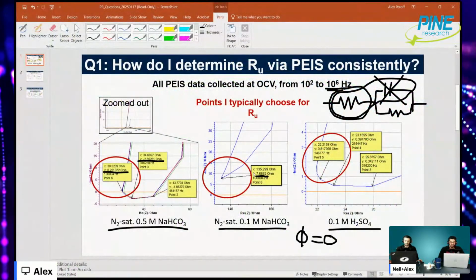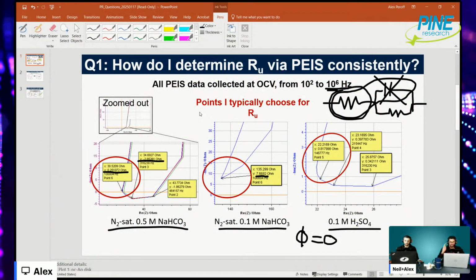And mainly, again, the key is you want to try to avoid relying on data points within that curl at the highest frequencies. I would be very hesitant to pick a point where it's going backwards, so to speak. Those points don't really relate to reality. It's circuitry artifacts, reference electrodes, stuff getting in the way. It's not really related to your potentiostat or your solution resistance much. So I would be very hesitant to rely on those data points, to be honest. Yeah, those are great points and things that I don't always think about. So that's the solution resistance.